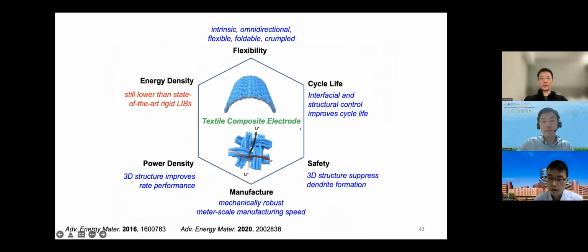What we have right now shows that the textile composite electrode, we believe, has lots of fun. It looks quite promising to make our battery extremely flexible. The cycle life is not too bad. We can engineer the structure, the microstructure and the mesostructure, and then the materials to improve the stability to at least 500 cycles, no problem. Safety looks like there are some advantages. Number one, you can suppress dendrite formation. In our lab, we don't really see too many dendrites. Number two, it can somehow hold electrolyte and does not allow it to leak out. On manufacturability, we tested a little bit and showed that it probably is promising to achieve a similar speed of manufacturing as we do in the battery industry.